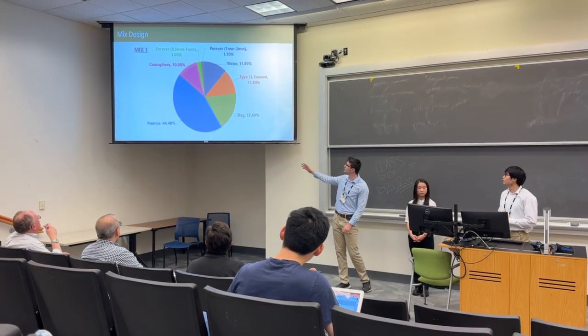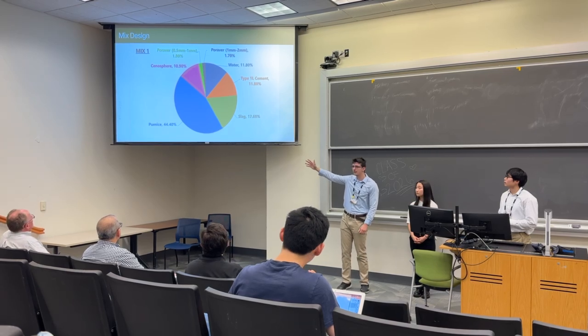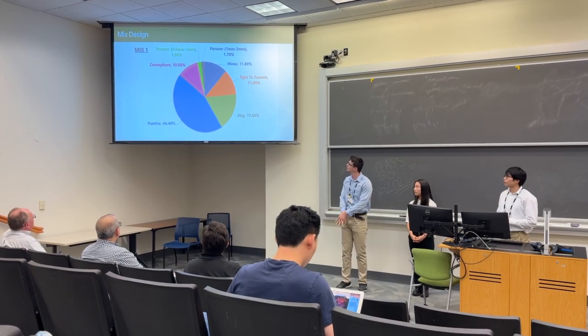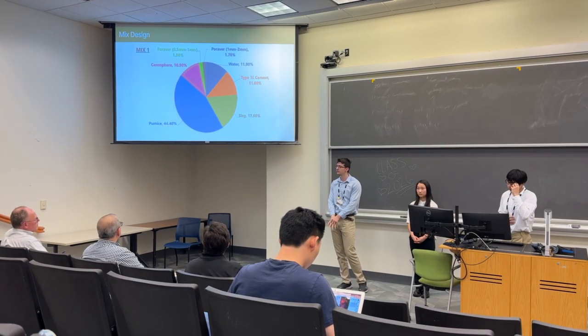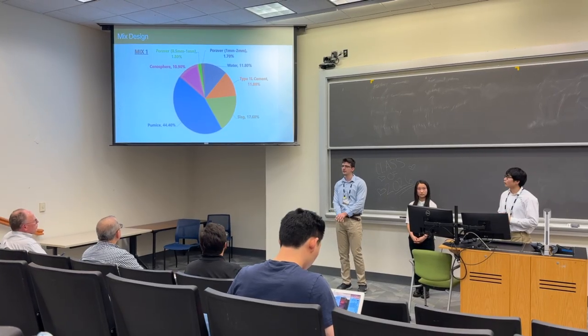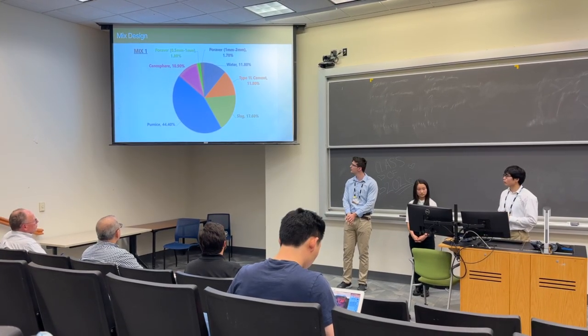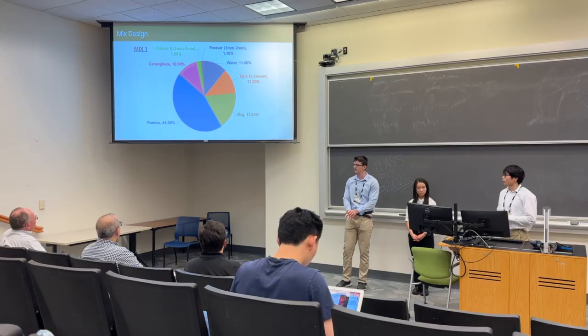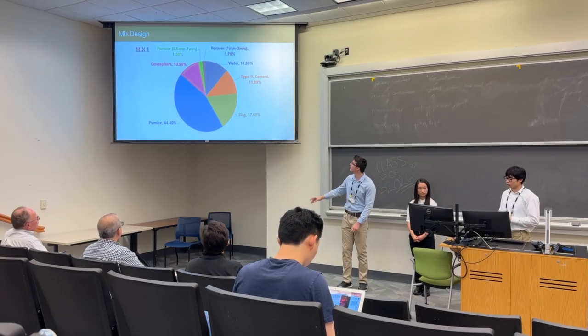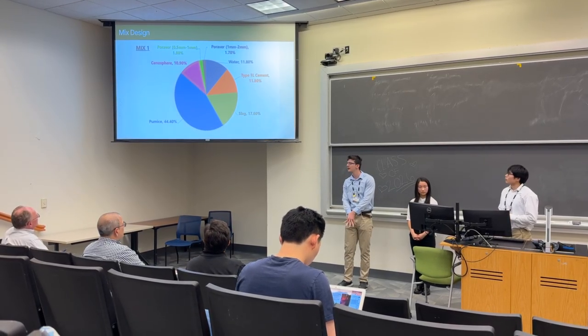This is the composition of the first mix. Our main coarse aggregate is pumice, and then our light aggregates include varying sizes of perlite and cenosphere. All three of these were chosen because they are lightweight and they have high compressive strength, which helps the end strength of the cement mix. And then for the cementitious materials, we use Type 1L and slag.